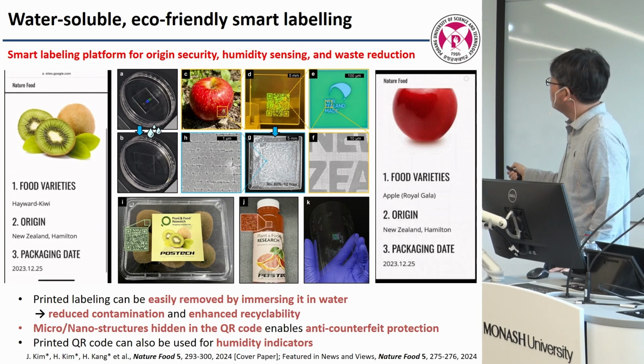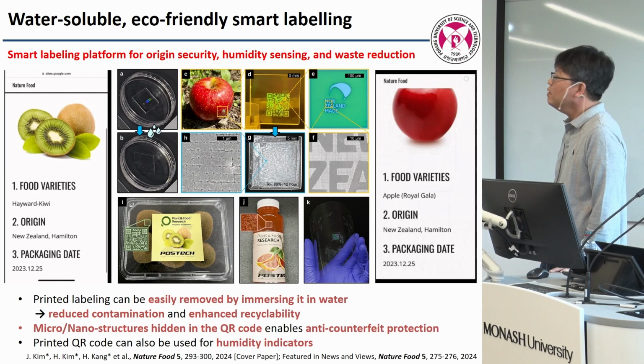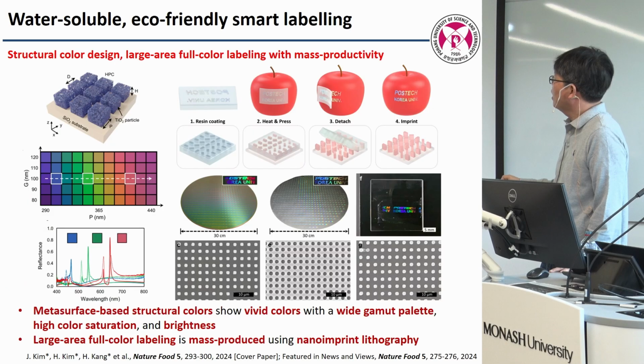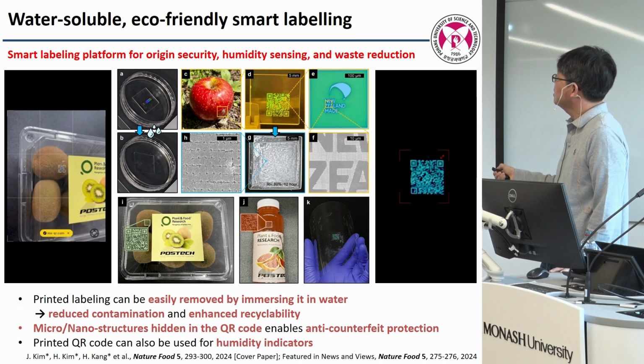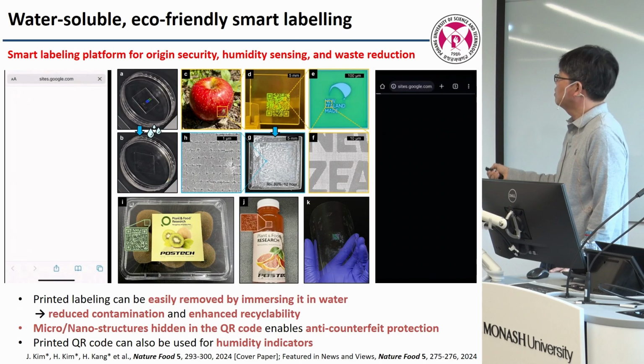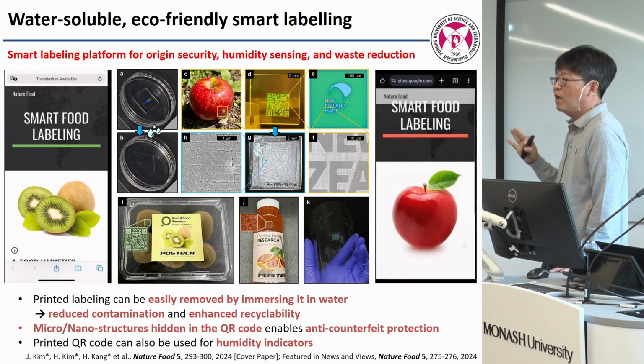And some of the hidden images use structural color, and sometimes we added some hologram function here. But the more beneficial part is that this is water soluble. So we mixed this nanoparticle into the water soluble polymer. It's non-toxic, and we can wash it with water before eating, so it becomes edible. So all the TiO2 is gone.